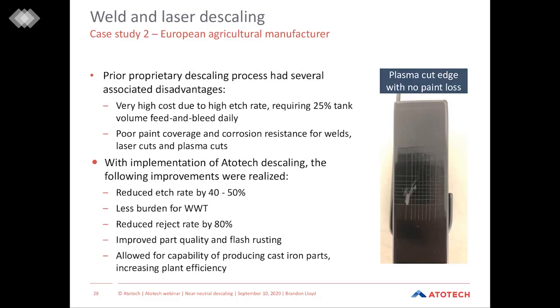So the second case study is a European agricultural manufacturer. Their prior proprietary descaling process had several associated disadvantages. It had a very high cost due to the high etch rate, requiring approximately a 25% tank volume feed and bleed on a daily basis. Poor paint coverage and corrosion resistance was often observed for the welds, laser cuts, and plasma cuts.